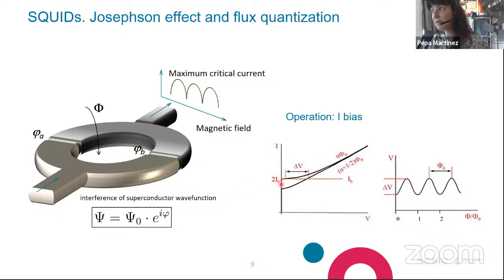This maximal critical current is a function of the externally applied magnetic field, being phi-naught periodic. This could be already used to measure magnetic properties, because one could measure at every point a current voltage characteristic and determine the maximal critical current. This is, however, not convenient at all from an experimental point of view, because you should perform this measurement at every point. What we normally do is to current bias the device at a current slightly above the maximum critical current, so that the device always works in the dissipative regime, and there is always a voltage that can be measured. And of course, this voltage will also depend on the flux threading the loop, being also phi-naught periodic.